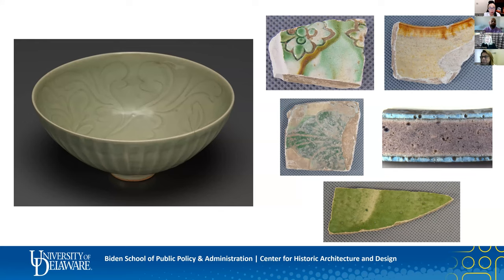So then we have to decide on sample size and field of view, which governs the spatial resolution that's possible and therefore affects which research questions we can reasonably tackle. Then we have to think about the questions that we want to investigate and decide on how many replicates to include and how those replicates should be defined. For example, if the field of view is small and the sherd material is very inhomogeneous, then you're going to need more within sherd replicates than you would for a homogeneous material.